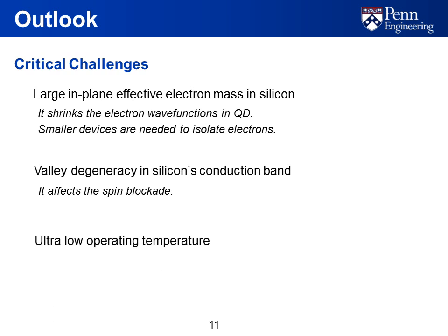Lastly, the manipulation of spin qubits in silicon requires ultra-low operating temperature, which means any defect or trapped charges that can be ignored at room temperature may be very important at such a low temperature. Therefore, ultra purity of silicon is required. We need very careful control of defects.